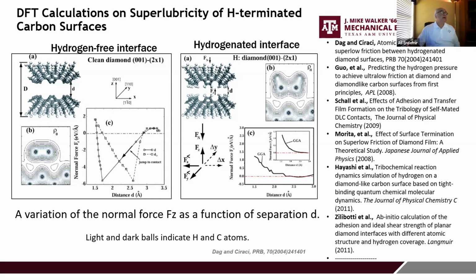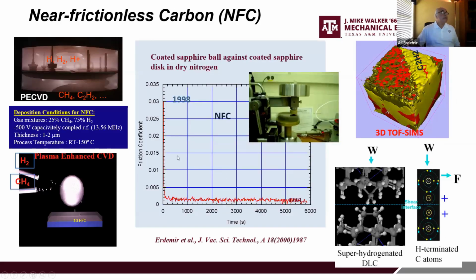So this corroborated as to what made these highly hydrogenated carbon surfaces super lubricious, or providing this nearly frictionless sliding condition. And of course, we did TOF-SIMS analysis of these surfaces after the test. The only thing we could see within the sliding wear track was actually only carbon and hydrogen.